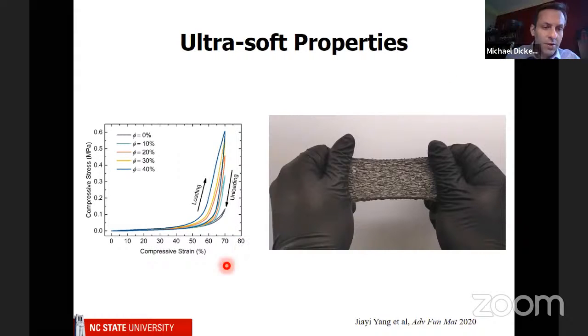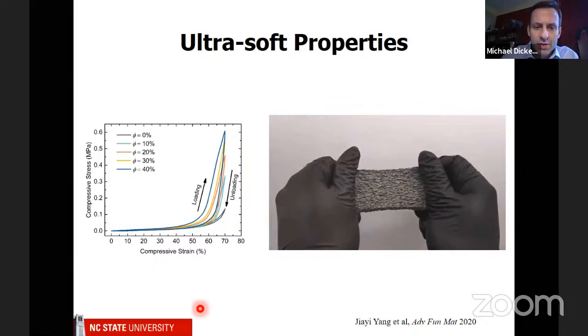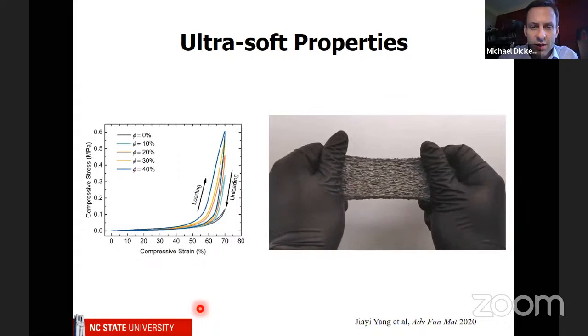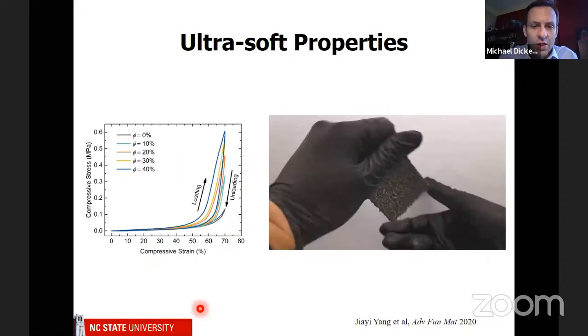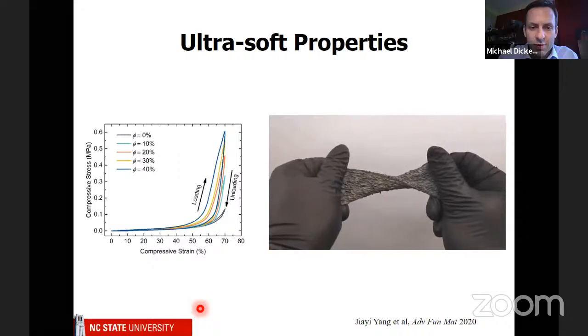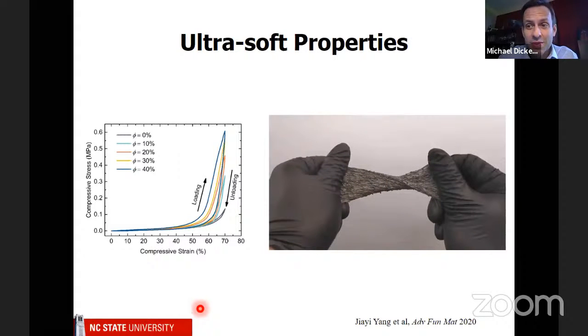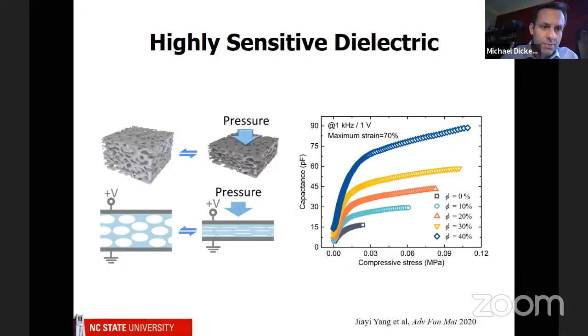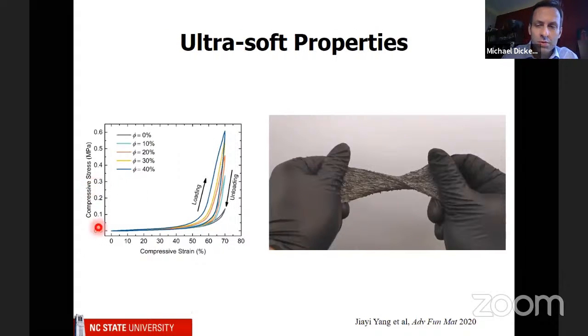Okay, all right, perfect. So we have this material, and this shows you what it looks like. It's very soft and stretchy, like a sponge, and you can twist it, and there's liquid metal inside of it, but it's not leaking because it's completely encased in silicone. And when you squeeze this, it's quite soft. In fact, if you measure the stress versus strain, it doesn't require very much at all until you push all the air out, at which point the stress goes way up. So this is another example of a J-shaped curve.